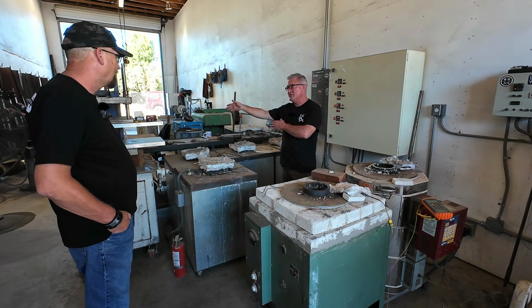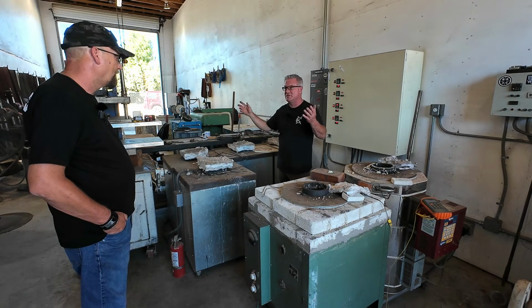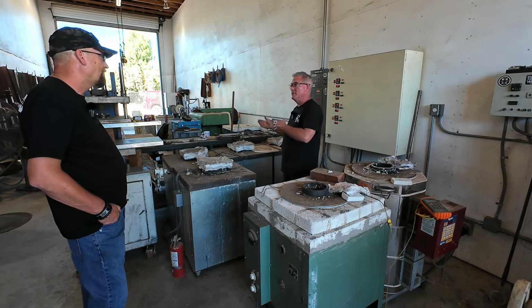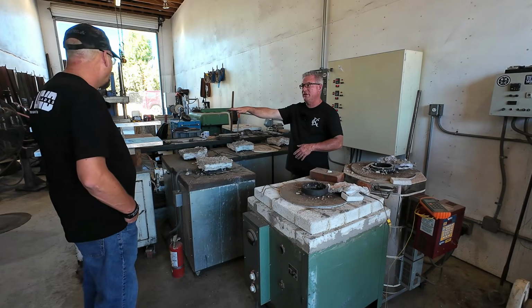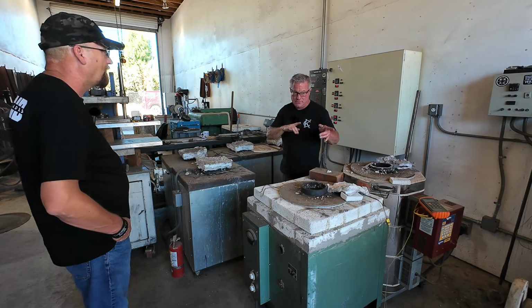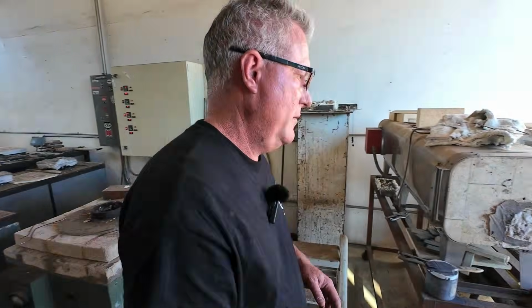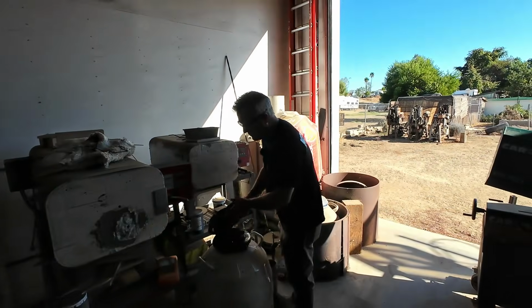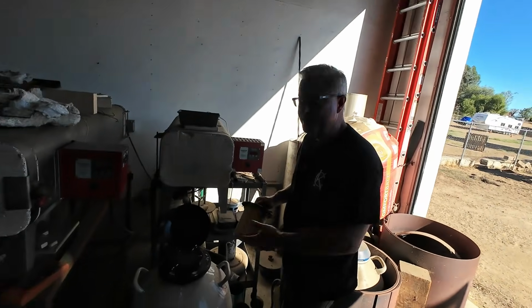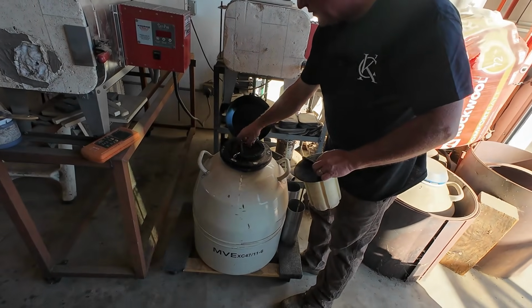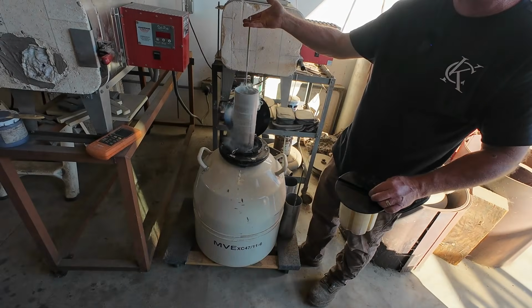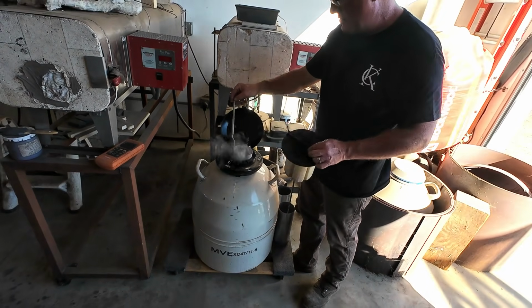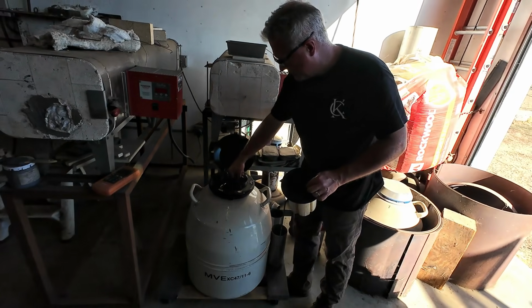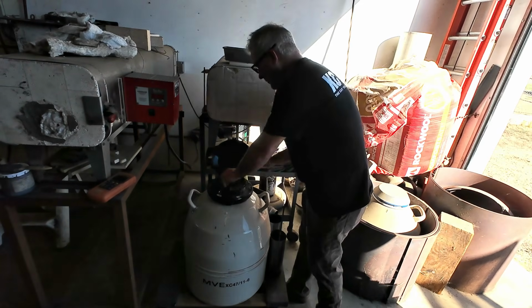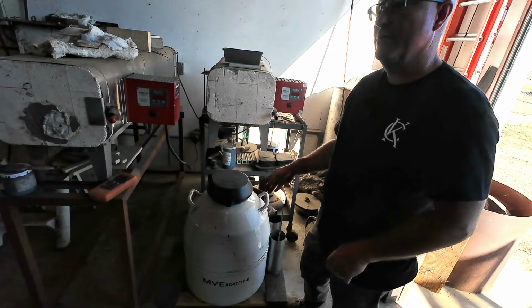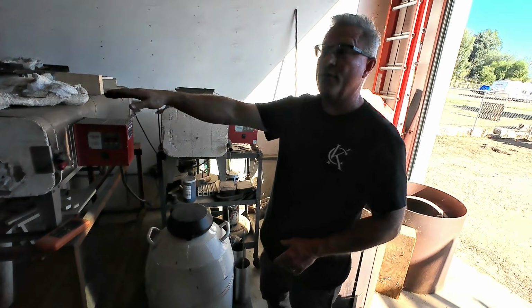Then from here, it gets quenched into one of the salts at a specified temperature. Then it comes out, and depending on how thin it is, it might go into that plate press. Then it goes over here, and I do not do a snap temper. So then it goes into liquid nitrogen. These are fairly large tanks, so I can put blades in there. It goes into the liquid nitrogen for X amount of hours, then out of there, air cooled. Then it goes back to the salt for temper.